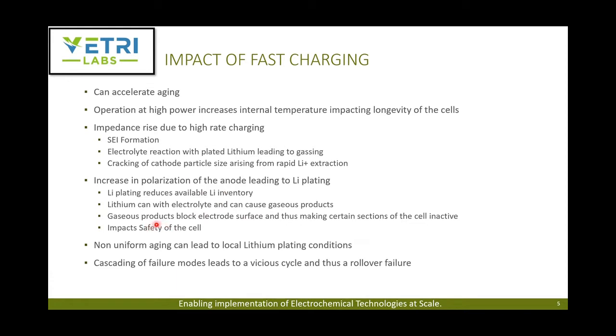And then that's what is covered here. And the other thing that this leads to is the lithium plating can lead to a dendrite formation of lithium, poking through the separator and then shorting the cell. This can also be impacting the safety of the cell. So these are the impacts of the lithium plating.